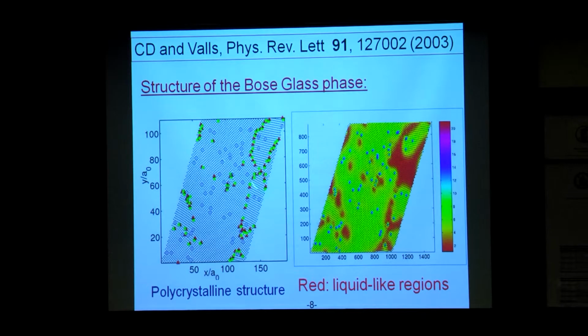I have not given you the details of this calculation. One gets something that is called the local Debye-Waller factor. Basically, we look at the average position, and then you look at fluctuations about that position, and you have some kind of a Gaussian density, and the width of that Gaussian density profile gives you some degree of localization. Somewhat similar to the Lindemann criterion that one uses to distinguish between a solid and a liquid.